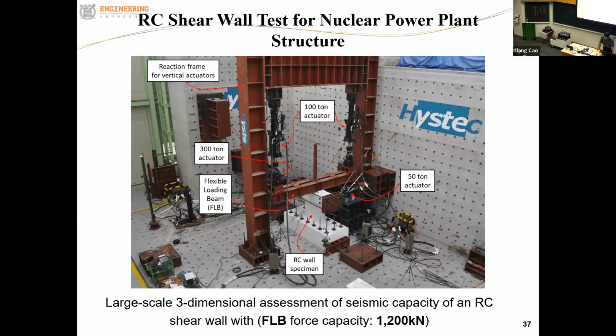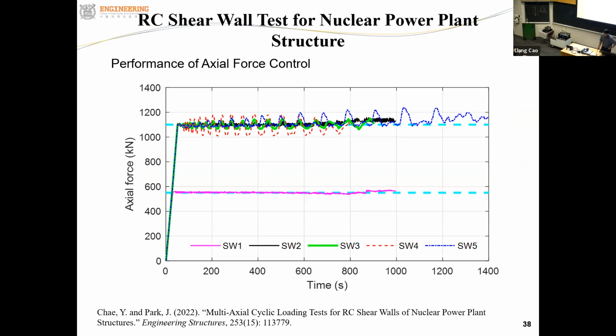And this kind of test was very challenging in the existing study because it was difficult to construct the test setup like that. And also it is difficult to apply the axial force when the in-plane and out-of-plane motion are applied at the same time. But by using the flexible loading frame and the newly developed force control algorithm, we were able to successfully conduct this test.